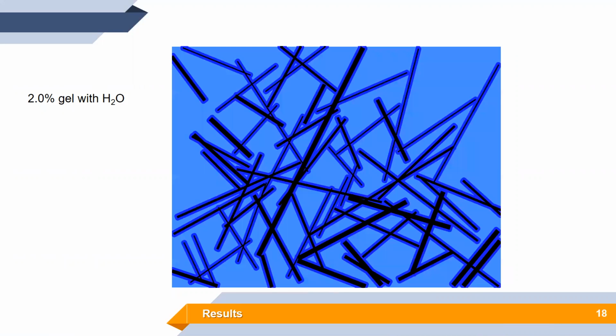And when we think about the solvent, how it behaves or where it is, we can find that it actually exists at two sites. First, it's in the free spaces between the gelator aggregates, in the pores, where the solvent behaves as a bulk phase. And there are also solvent molecules close to the surface of the gel network that interact with it. Because, as you maybe remember, the molecular structure of the gelator is a polar molecule which creates a polar surface. On top of it, there are hydroxyl groups, which very easily interact with other solvents, for example, water.